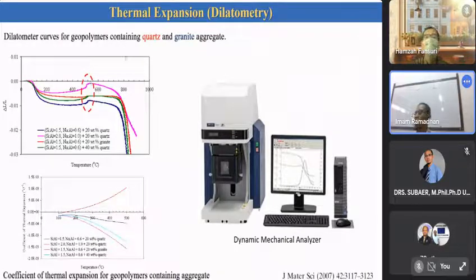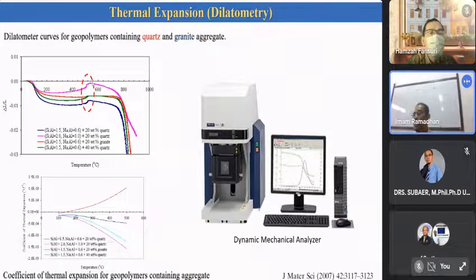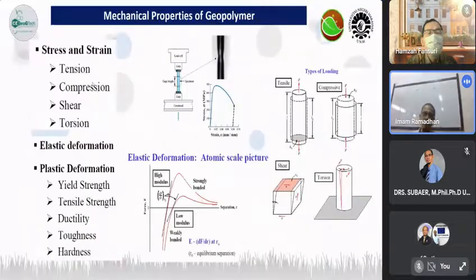So this is a good finding actually at the time, and we needed a lot of effort in order to interpret this one. Then we discussed this result with other researchers, and we confirmed that this is because of the expansion of quartz inside the geopolymer, more rapidly than the bulk of geopolymer, the matrix of geopolymer itself. So, yeah, please consider it as one of the topics that you can explore more.